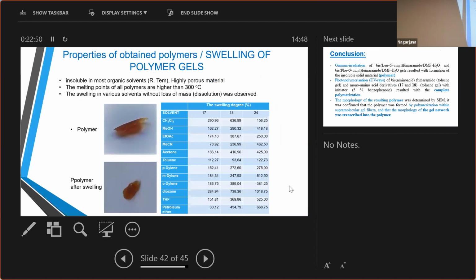Okay, here are the properties. These new polymers are insoluble in most organic solvents. They are highly porous materials. The melting point is higher than 300 degrees, and these compounds have the possibility of swelling in various solvents, which you see here. Here's a picture of SEM polymer and polymer after swelling. Here are quantities of solvents that these new polymers carry.